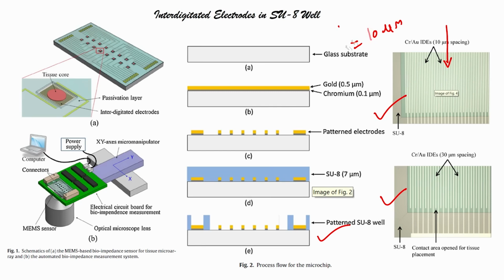I have used the glass. So, I have taken the glass substrate, correct. Then I have deposited chrome gold, easy. Then after chrome gold I have spin coated photoresist, right. Then I have pre-baked it, this is positive photoresist, positive. Then I have pre-baked it at 90 degrees.